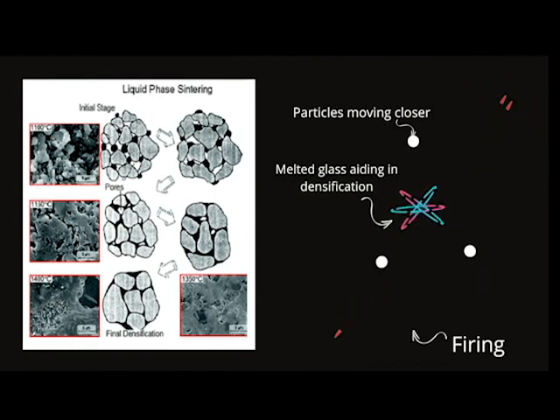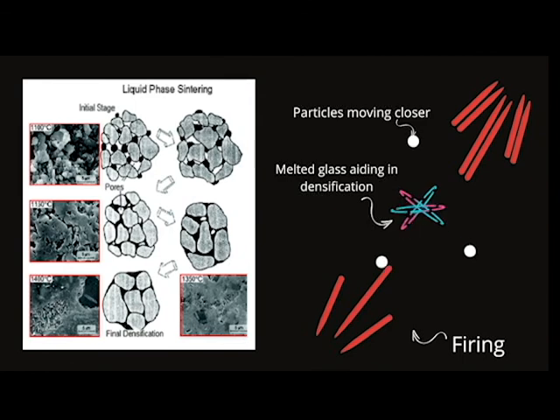In understanding the sintering process, the liquid phase sintering with waste glass contributed to the decrease in pore volume. It is because waste glass supporting the densification of the bricks liquefies and fills the gaps and aids in adhesion between particles.